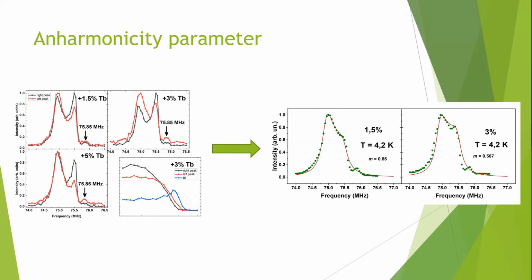But what can we say from these three samples? We can say that there is a spatial spin modulated structure. We can say that the signal is very, very intense. The signal on iron is very intensive, and the frequencies of the peaks are stable. So the anisotropy of the spatial spin modulated structure doesn't change.